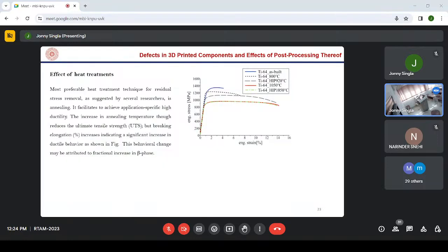If you see this blue line, this is the as-built material having high strength, but ductility is low. But this red line and this green line correspond to annealing at 1050 degrees Celsius, and the green line is a hot isostatic process, which we will discuss later in detail. In case of titanium alloy, this happens due to an increase in the beta phase. Alpha and beta are the two phases in titanium alloy, so when we increase the beta phase, ductility improves.